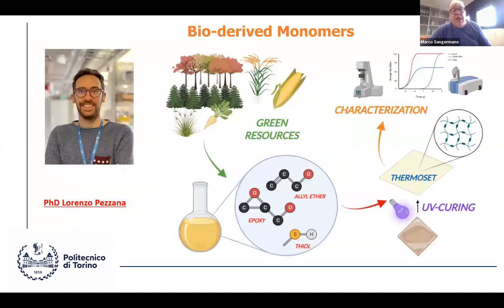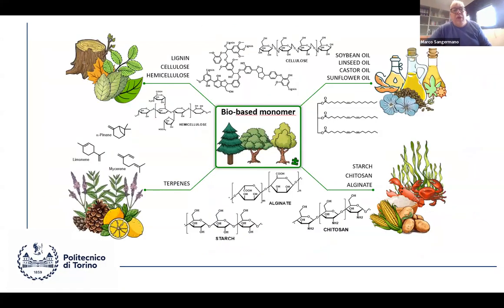It was work done by my PhD student, Lorenzo Pezzana, and the idea was starting from a bio-based precursor, inducing some functionalization, using this functionalized precursor to get UV-cured thermosets, and making the characterization of the UV-cured thermosets. We can start from many different resources, from plants, getting lignin, cellulose, hemicellulose, which can be further functionalized and exploited in UV curing.